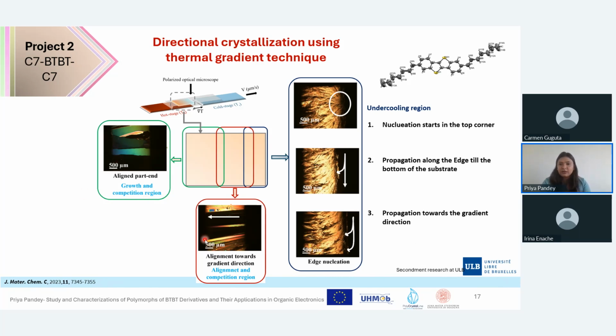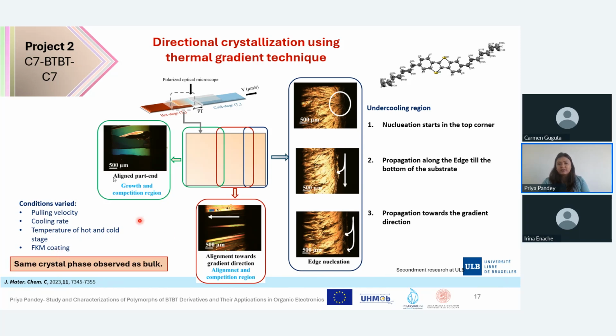And as I mentioned, we can vary a lot of conditions in this kind of technique, like pulling velocity, where we can vary from 1 micrometer per second to 100 micrometer per second. Cooling rate, the temperature of hot and cold stages, and we can also apply a polymer coating between the substrate and the molecular layer. After trying all these conditions, again, we see that the molecule is stable in just one phase, the one we obtained in the bulk.